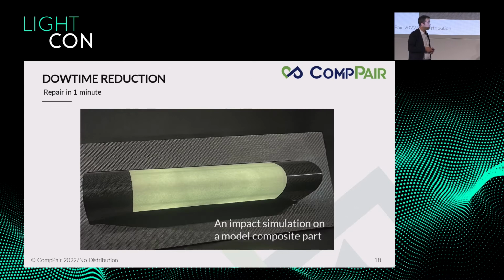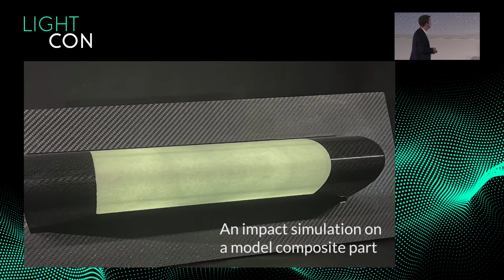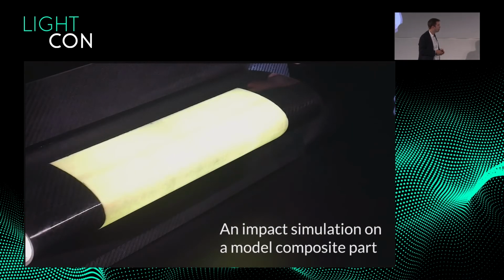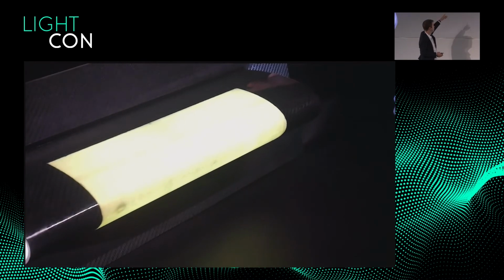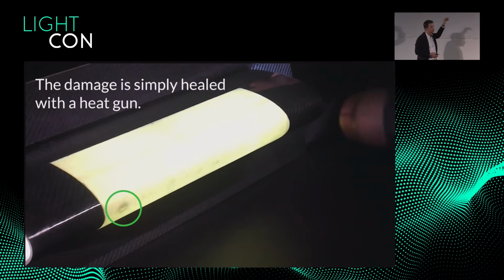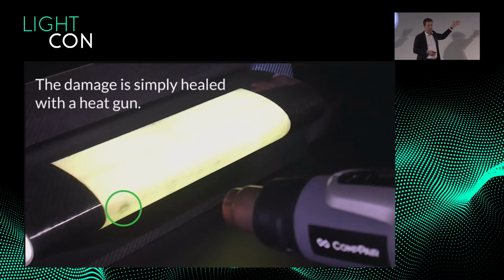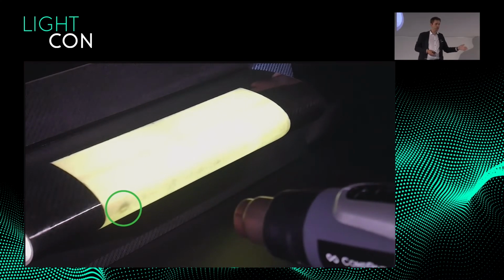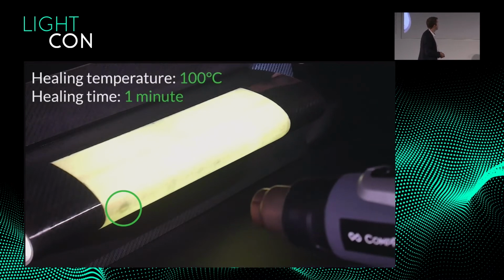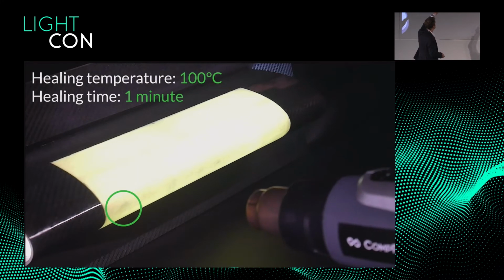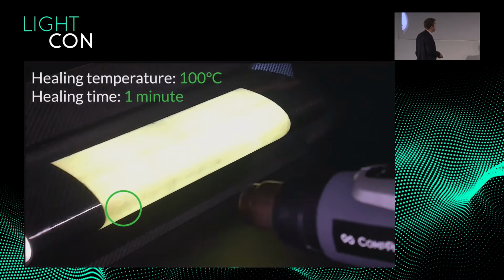We have the downtime reduction, and this is another video to show you that it works also on other types of parts or other geometries as well, where we impact. You see a typical impact here really on the edge, and we come again the same as before, and we just heal for 1 minute, and you will see that the damage will completely disappear right after in there.